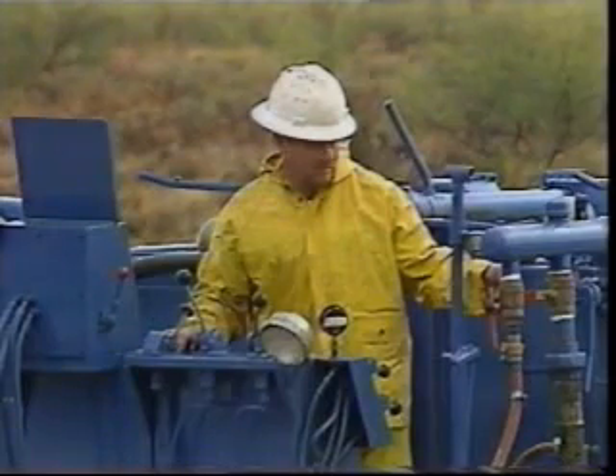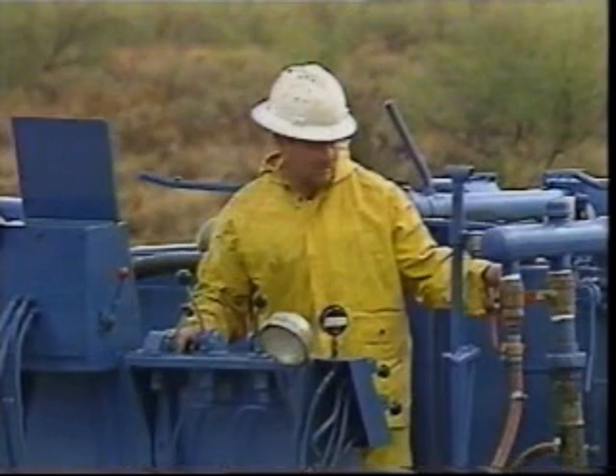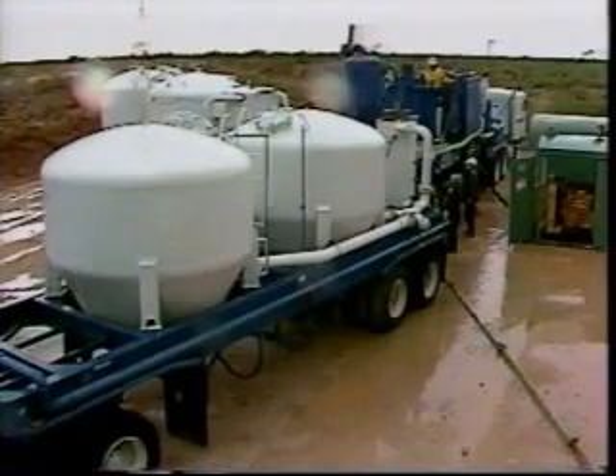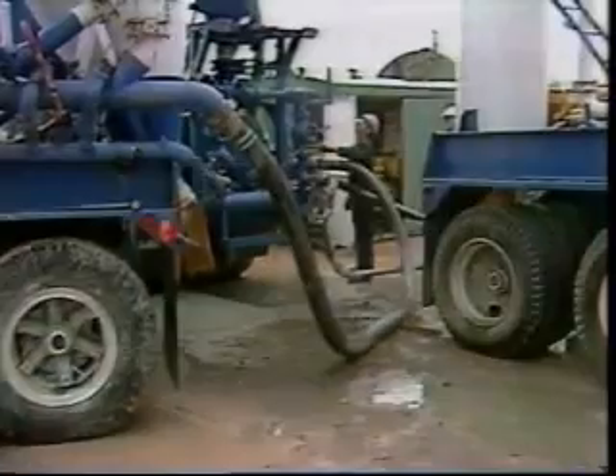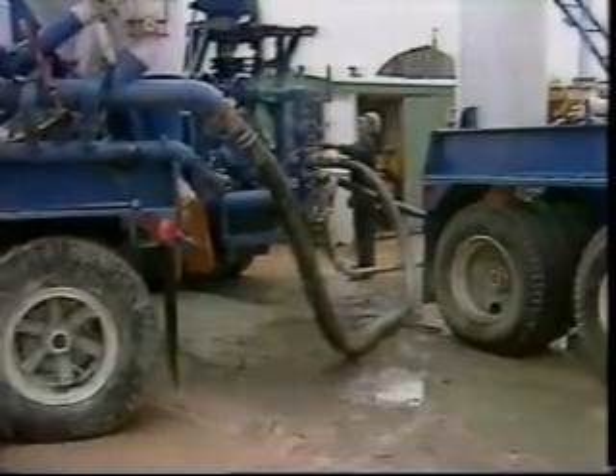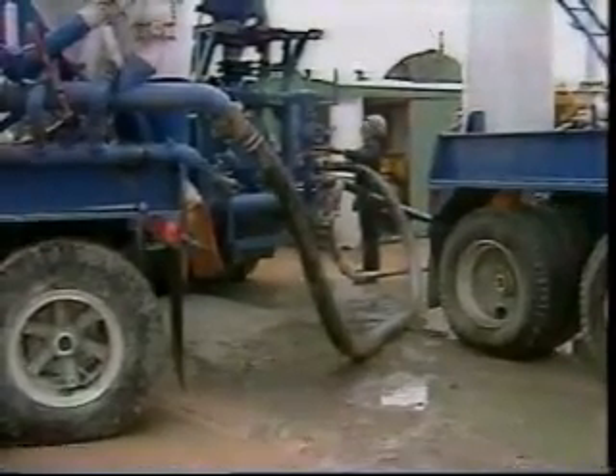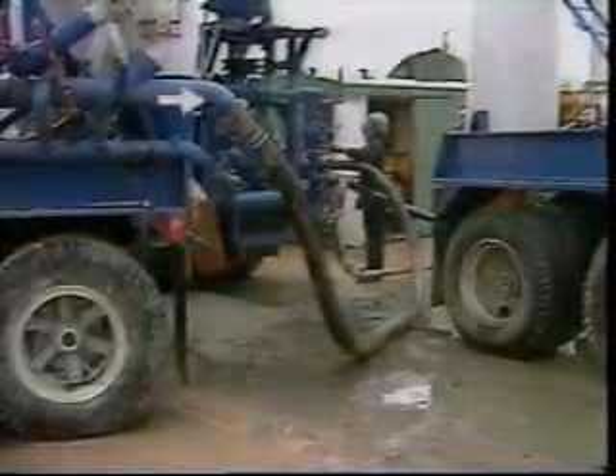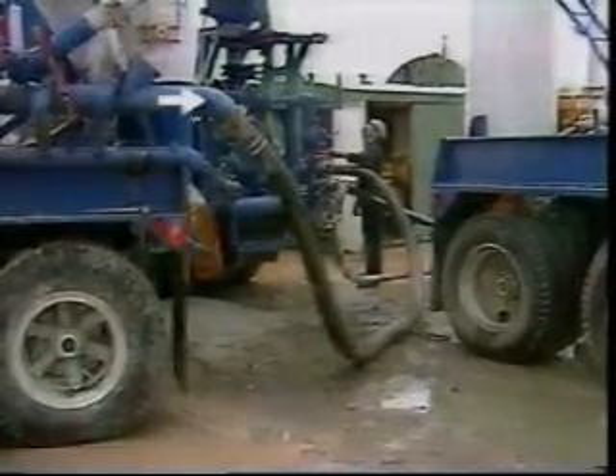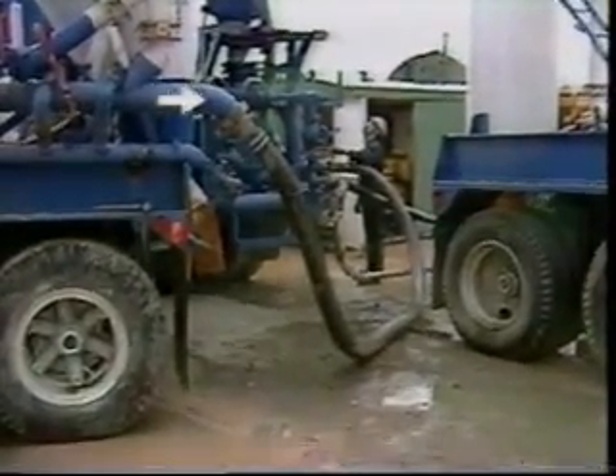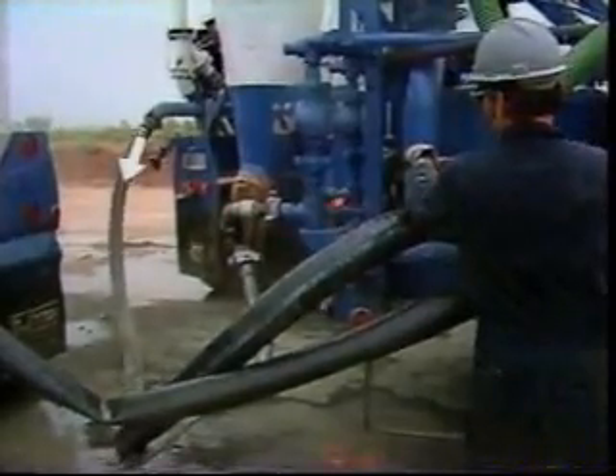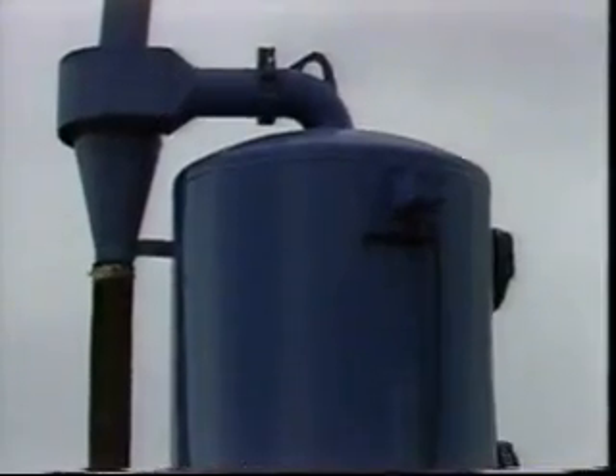Moments later, the operator is sending the lead cement slurry into the hole, immediately behind the pre-flush. This cement is designed with less density than the tail cement, so that it will exert minimal hydrostatic pressure on the lower zones. The slurry mixing and pumping process will continue for about 45 minutes. Pressurized air forces dry bulk cement out of the bins on the lead cement transport, through the discharge line, and up into a surge tank on the mixer at the rear of the pump truck.